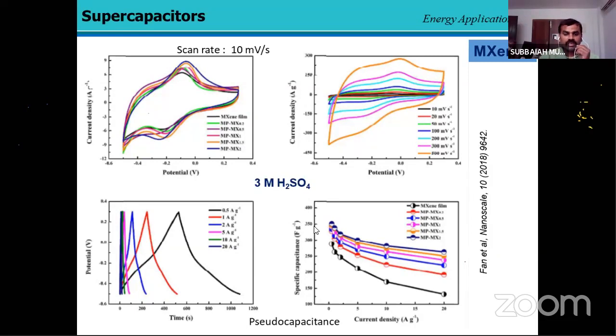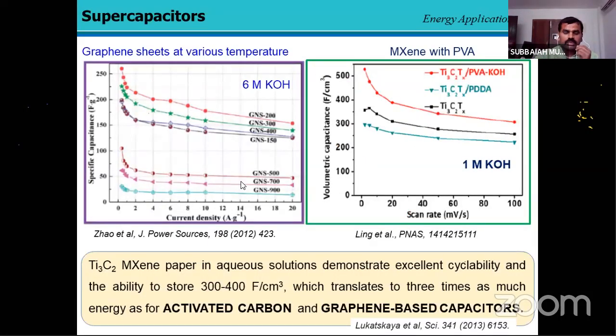They showed the specific capacitance is more than 355 farad per gram with a scan rate of 10 millivolt per second with the help of 3 molar sulfuric acid as an electrolyte solution. The mechanism mainly follows pseudocapacitance. If we use a neutral electrolyte, then it will form the EDLC mechanism also. Then the graphene-based materials. A group of people from China developed a graphene material which was compared with the MXene materials also. Initially they took the graphene sheet and heated it at different temperatures from 200 to 900.